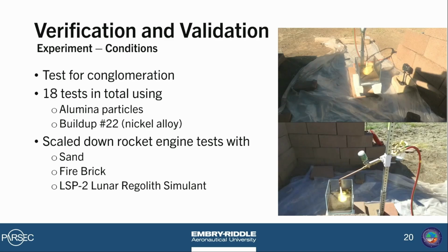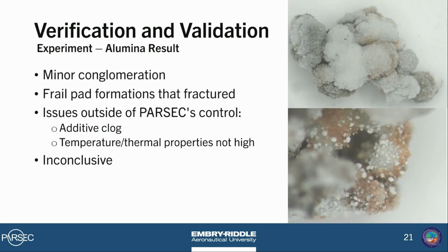The 3 different surfaces were sand, fire brick, and primarily our LSP2 lunar regolith simulant. Our first additive that we conducted tests with was alumina in a varying range of sizes. The additive was injected and deployed through the thermal sprayer onto the surface below. These tests yielded less than ideal results, with only 1 out of 18 of our tests resulting in conglomeration. Yet even that one test that formed a conglomerate was incredibly weak, and it was broken apart during our attempts to retrieve it from the testing basin. What remains is what you can see here, about a 0.11 centimeters squared section of conglomerated LSP2 and alumina.